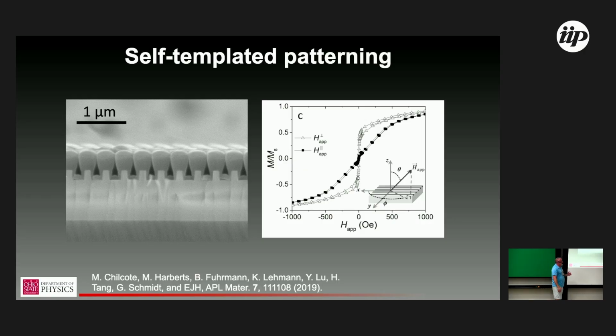Okay, so what we were trying to do was generate some in-plane anisotropy that we could use for engineering properties. And so the first check was DC SQUID, in-plane, two in-plane scans, parallel and perpendicular to the long axis. Again, another story I'd be happy to expand on over coffee, but this graph took us two years to understand, because it's kind of hard to see, but H perpendicular is the open symbols, H parallel is the closed. So perpendicular to the nanowire is the easy axis, which is 100% opposite what your intuition would predict for these kinds of structures.